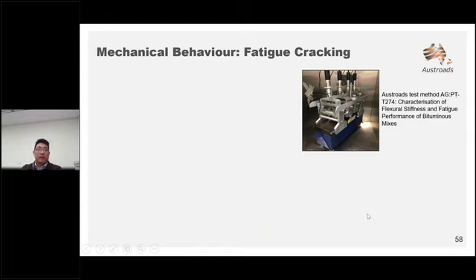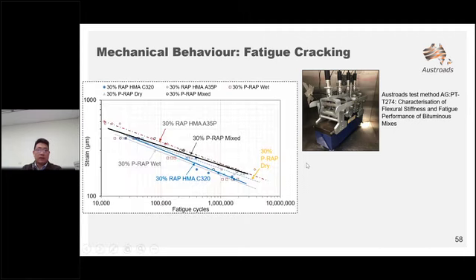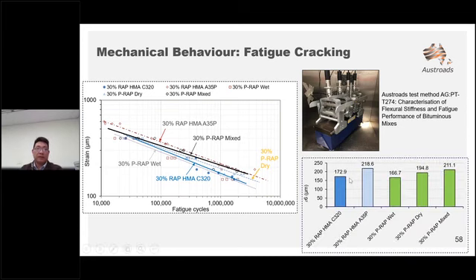So next we look into the fatigue cracking. The samples were run at different strain levels, and the results of the strain level and fatigue life were used to build the fatigue curve as in this figure. The value of the strain at which the beam reached the fatigue life of 1 million cycles is called epsilon 6, and the value of epsilon 6 was used to compare the fatigue resistance of asphalt mixes.